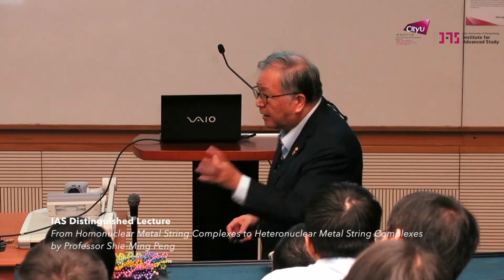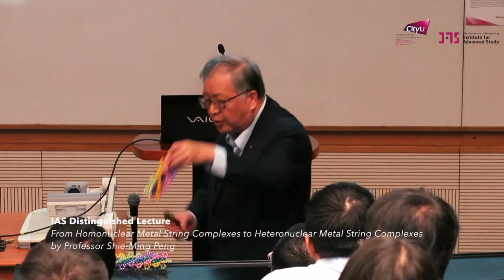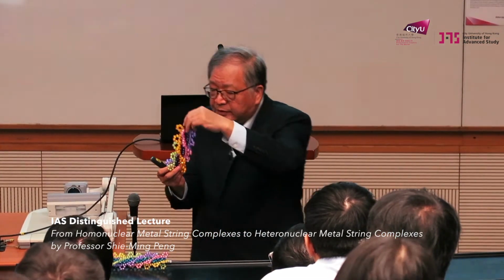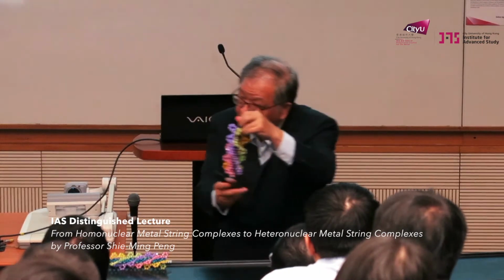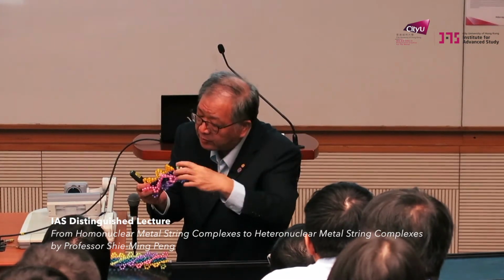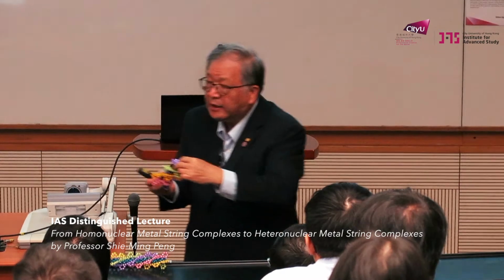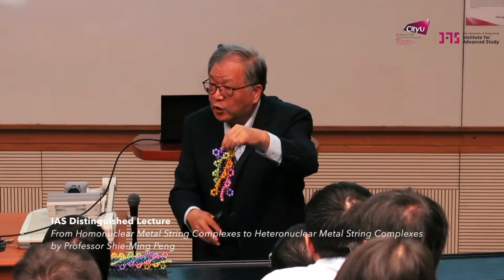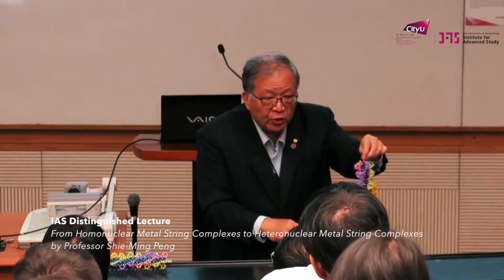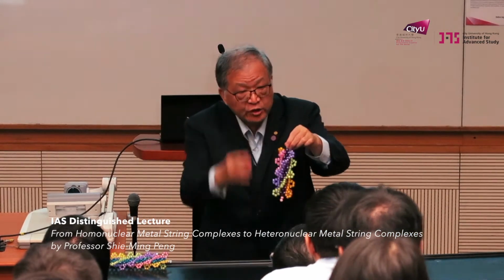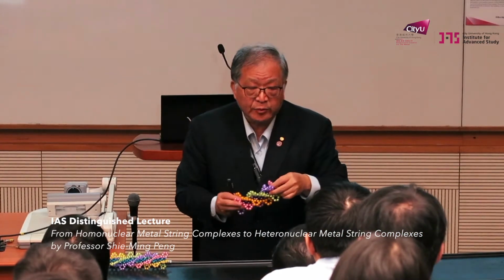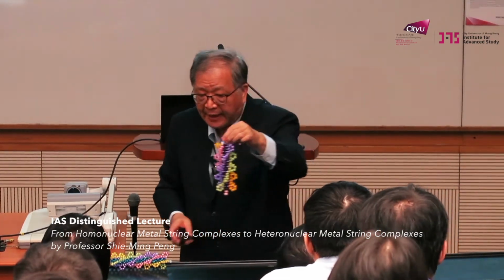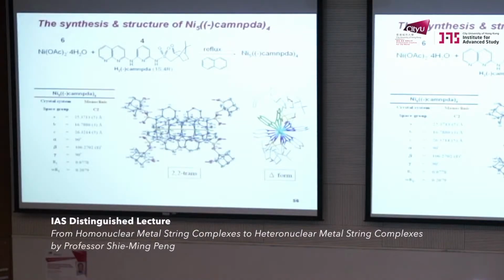Another thing is the chiral control. As I mentioned, helically, they are chiral. They have left-handed and right-handed. Normally, you get a racemic mixture. And this racemic mixture crystallizes in a centrosymmetric space group, which we call racemic. Okay, but we use this induced chirality.